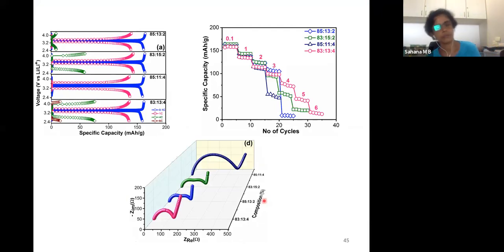Okay, let's see the electrochemical performance of these materials. Here we have added carbon black first to the NMP PVDF mixture, and then we added LiFePO4. We have seen the electrochemical performance of this material with varying concentration of the active material, that is LiFePO4. You can see here, in A, 85 corresponds to 85% of the electrode being active material LiFePO4, 13% carbon black, and 2% PVDF. And in some places it is 83, 15 and 2; 85, 11 and 4; and 83, 13, 4.